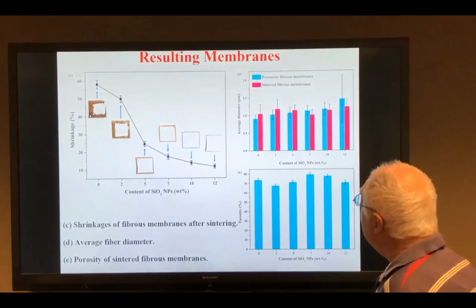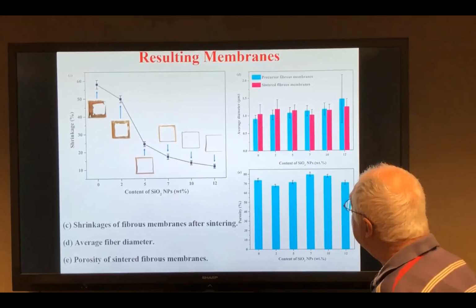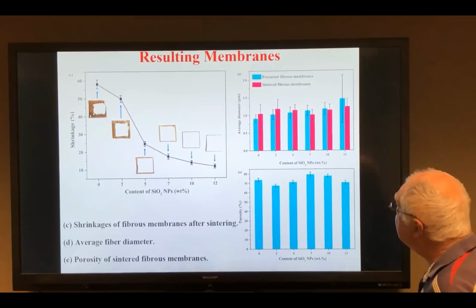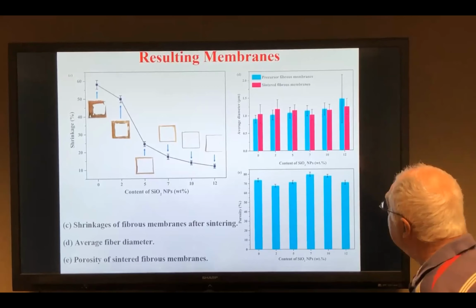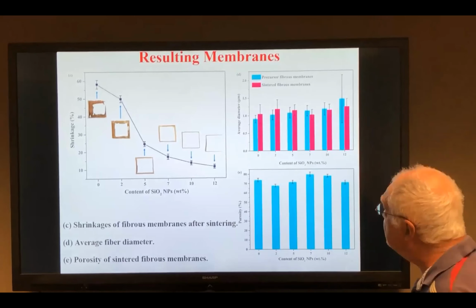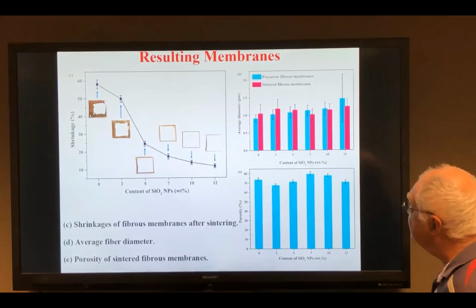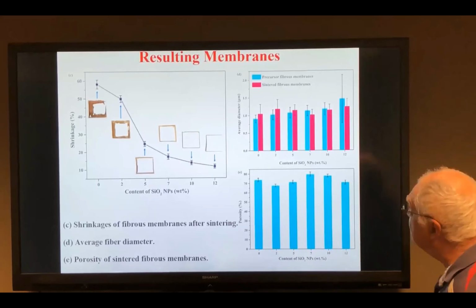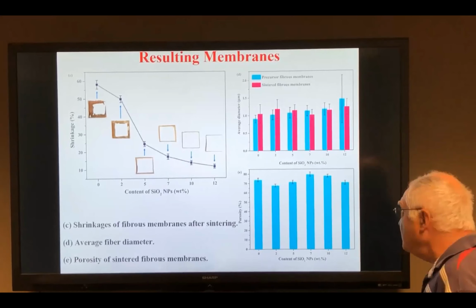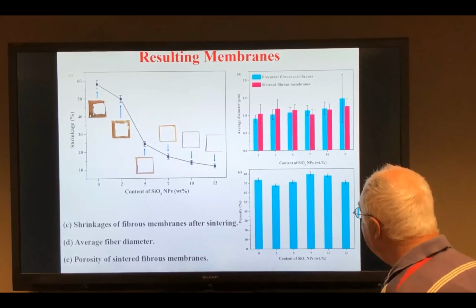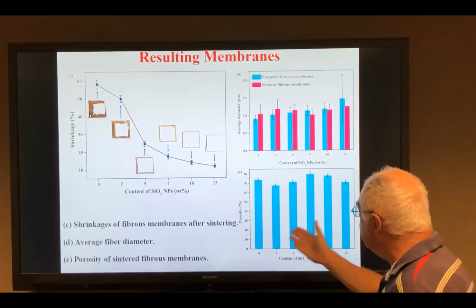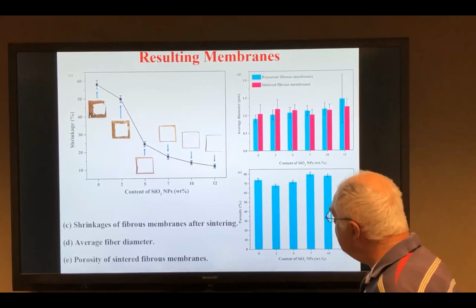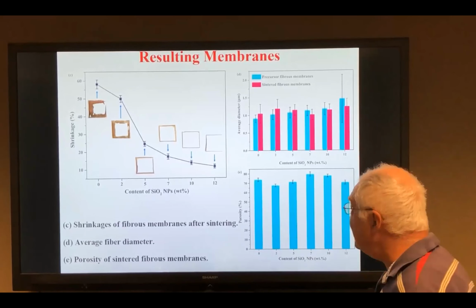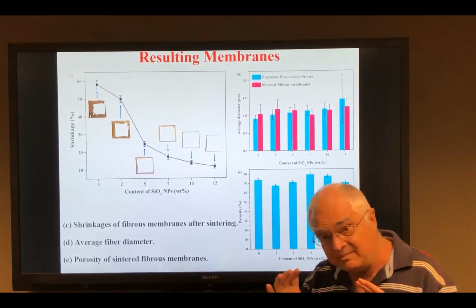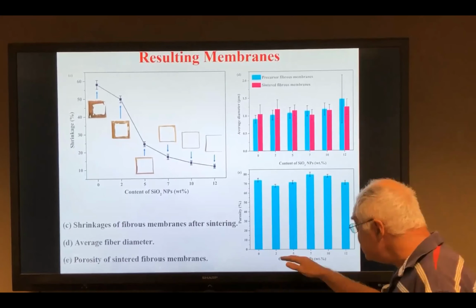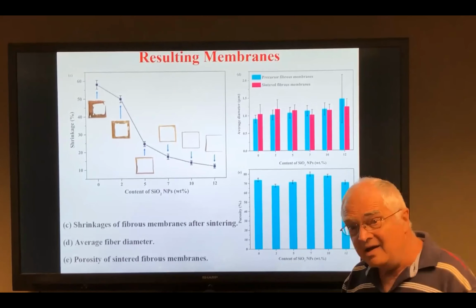So then you also expect to find the fiber diameter. The fiber diameter before sintering and after sintering is illustrated here. We are talking about fibers of diameters a little bit submicron or micron size. So this I would call microfibers, not nanofibers. Now regarding the content of glass particles, you also see some tiny variation of porosity, so this is good. Essentially, it means that at all these glass bead contents, you keep the general architecture of the membrane.